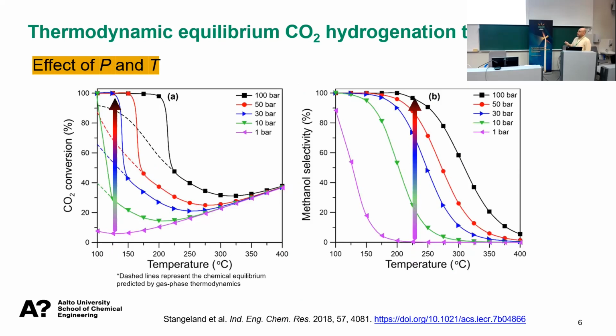So in panel A, I show you the CO2 conversion versus temperature, for 5 different levels of pressure. And on the right hand, you can see the same thing, but for methanol selectivity. So you can see that at higher pressures, for example, if you look at the 100 bars, we can increase both the CO2 conversion and the methanol selectivity. So the pressure has a positive effect in both. And in a similar way, if we go to lower temperatures, we can maximize the production of methanol.